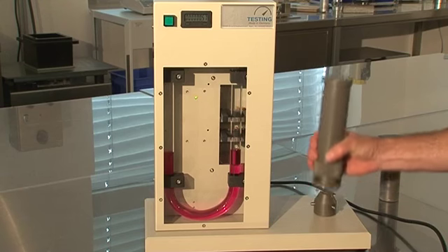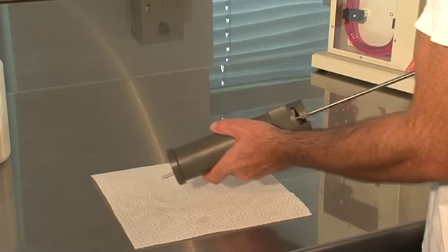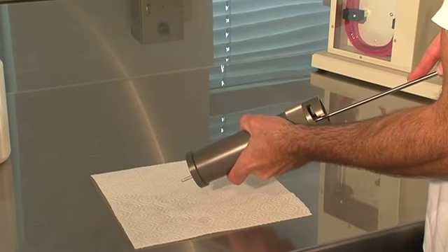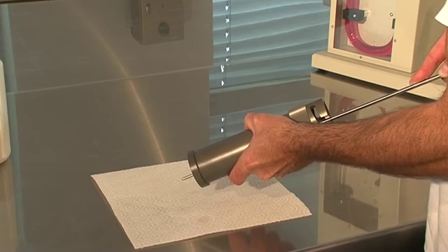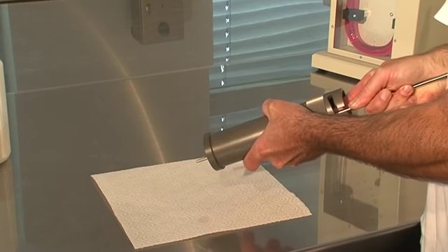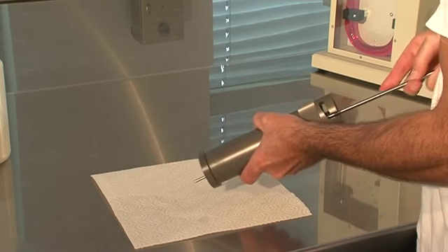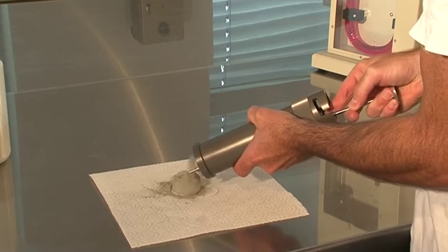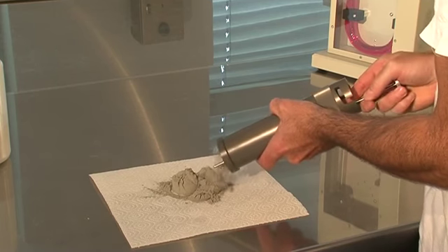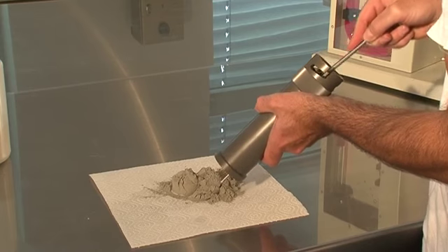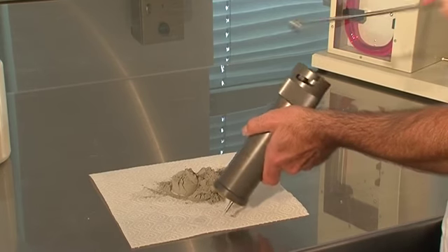Time and temperature are noted. The measuring process is repeated and the results are again noted. The sample is pressed out of the measuring cell and a second sample is prepared as before from new cement and also tested twice. Note the results of the lead time and temperature.